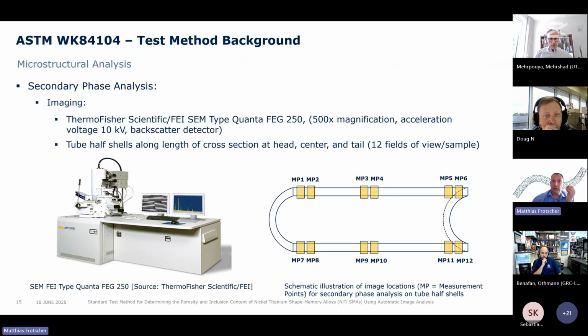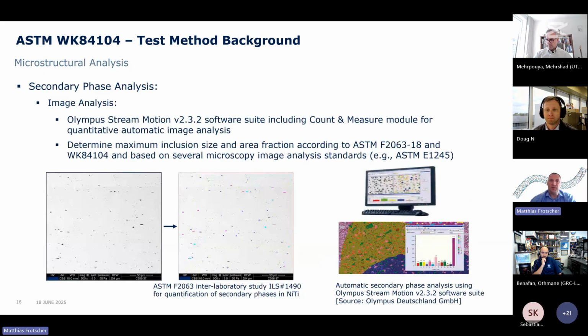The following example evaluating tube half shells shows how the method and principle works and how it can be applied to screen and compare different suppliers and material qualities. In this case, tube half shells were evaluated using SEM images, and you see the sampling locations in this schematic drawing here on the right-hand side. And then SEM images were taken using element contrast and backscatter mode. And subsequently, we did image analysis using image analysis software that can help to identify and quantify the inclusions. Automatic classification can be used to determine the particle size and area, and many additional analysis parameters like total particle area, roundness, and so forth can be evaluated. There are some commercially available software packages out there that can analyze up to 100 different parameters in a microstructure.